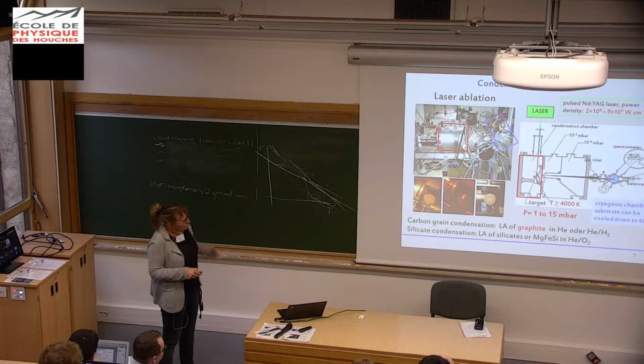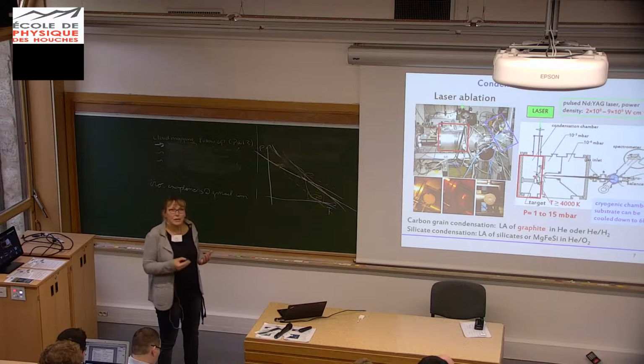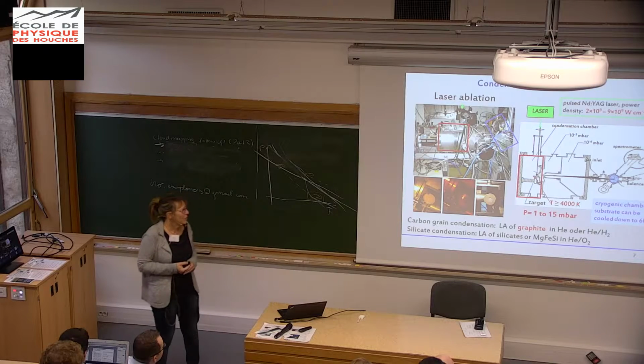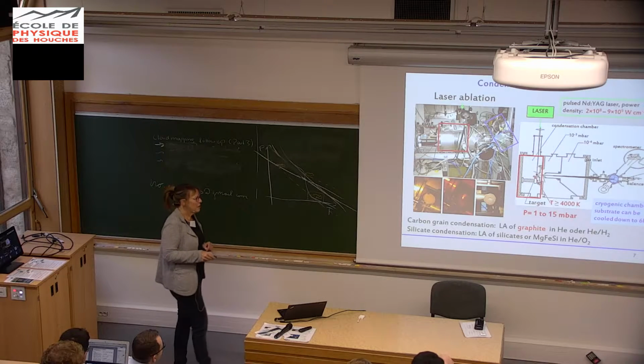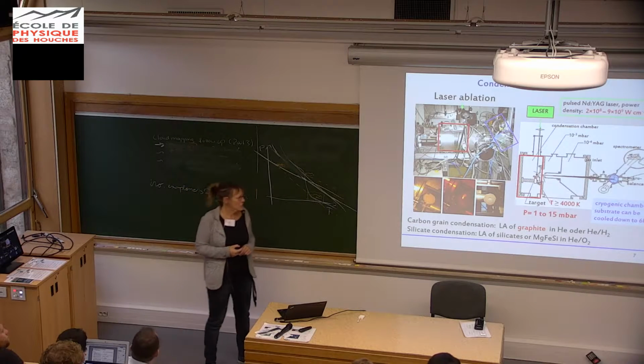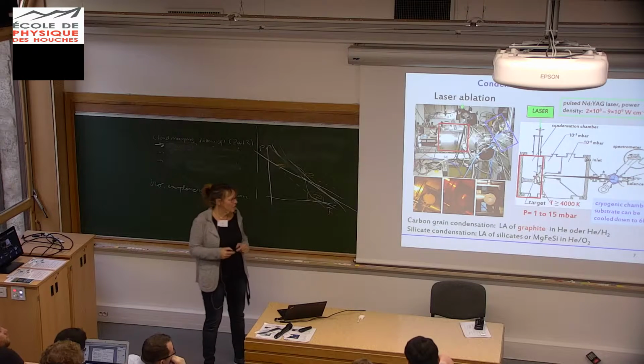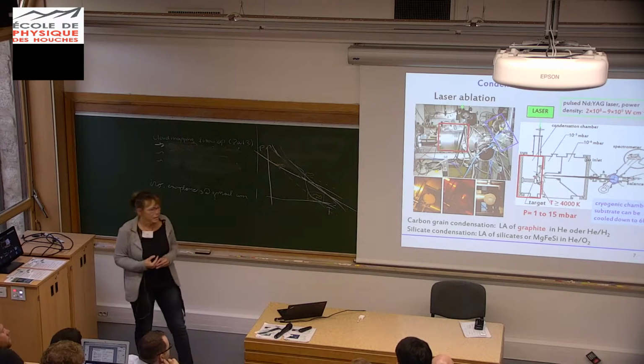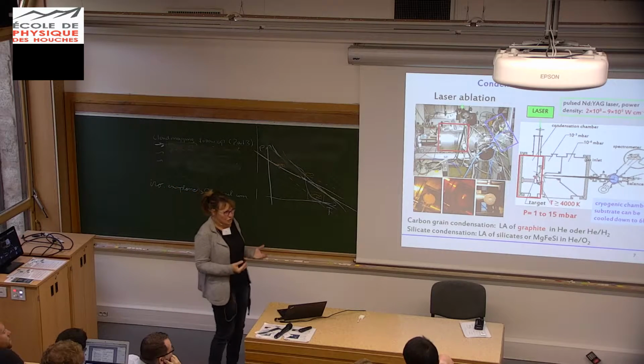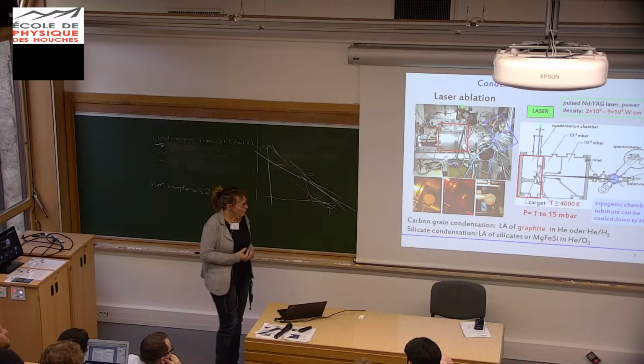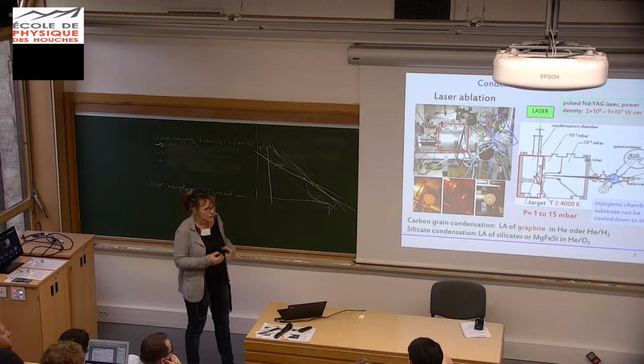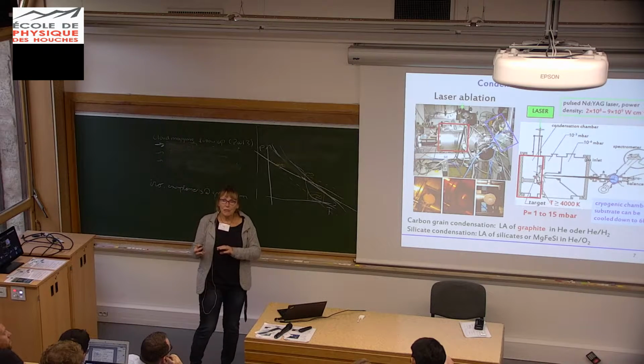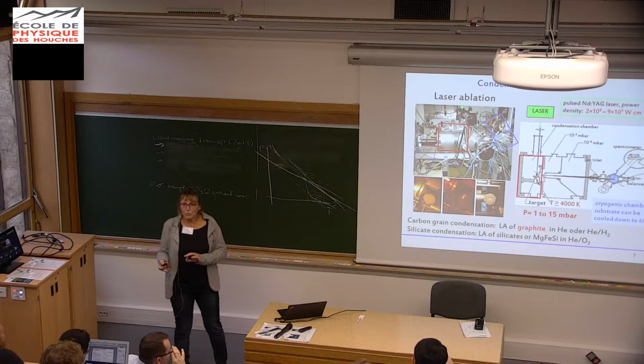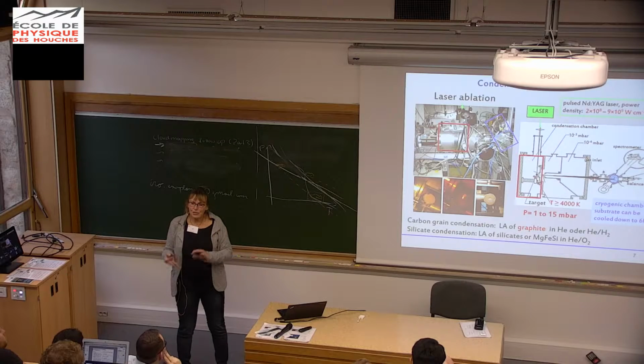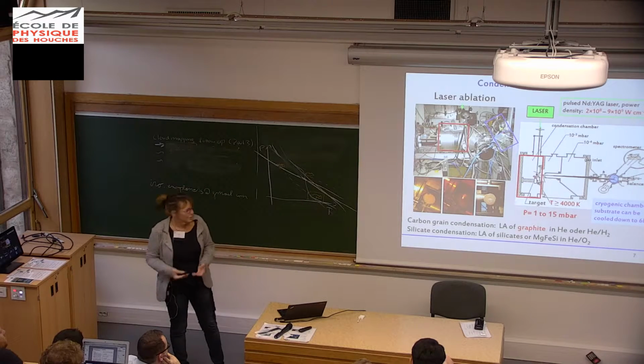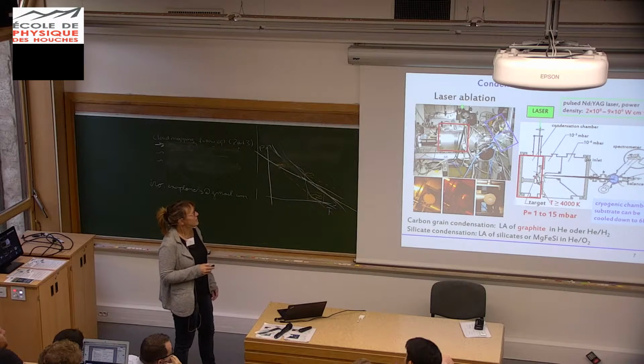If we want to produce something like silicates, we start either with a silicate and condense in a helium atmosphere, or we use metallic targets and condense in an atmosphere containing oxygen. By this process we can also control the oxygen content in the final silicate. We can work in a very oxygen-rich atmosphere, or we can go to a very deficient atmosphere, so that we can influence the composition of the silicates. For example, we can produce oxygen-deficient silicates which might contain metallic iron components, and these kinds of things are possible in this setup.